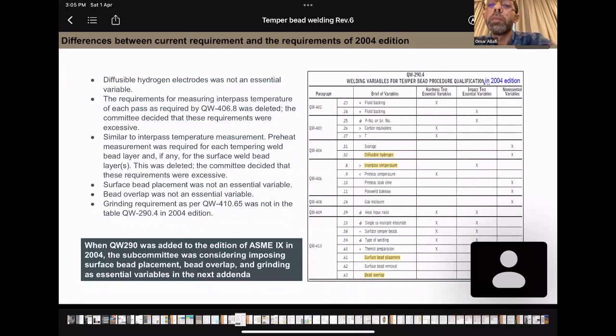Similar to interpass, the preheat temperature of each layer was also deleted. That doesn't mean, of course, that preheat is not required, but there was an additional requirement to control the preheat of each pass. So this was deleted. Surface bead placement was not an essential variable. Grinding requirement was not an essential variable. Which means that if the WPS was qualified for half bead technique, you can use it for full bead technique. So now this is not possible in the current edition.